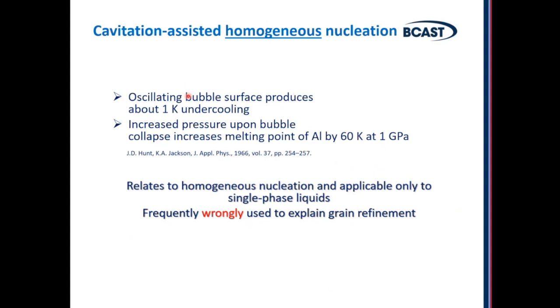On the other hand, the oscillating bubble surface before collapse also produces some undercooling, and that's relatively small undercooling, about 1 K. In a fundamental work by Hunt and Jackson in 1966, it was suggested and shown experimentally that this effect, the collapse of a bubble and increase of the local melting point, is a leading mechanism of homogeneous nucleation. But in liquid metals, homogeneous nucleation almost never happens. So you cannot use this explanation for explaining grain refinement in real melts.